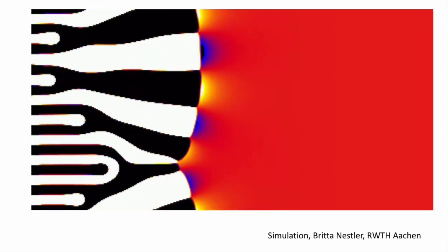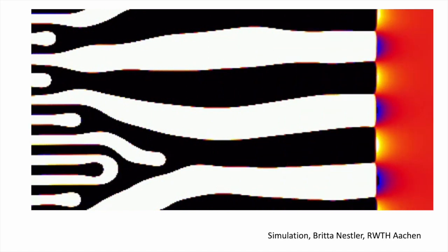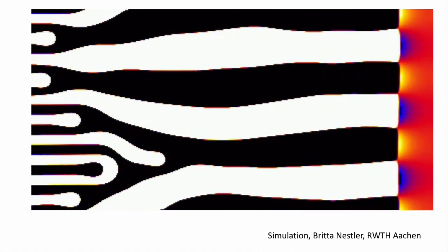Now, I'm going to show you a simulation of a eutectic mixture growing from the liquid. Here we have the black and the white phases growing at a common transformation front from the red liquid. And I'd like you to notice the diffusion fields ahead of the black and the white phases. This is the diffusion field of solute. One of the phases is rich in solute, and the other one is poor in solute. So we get diffusion simply in this direction.